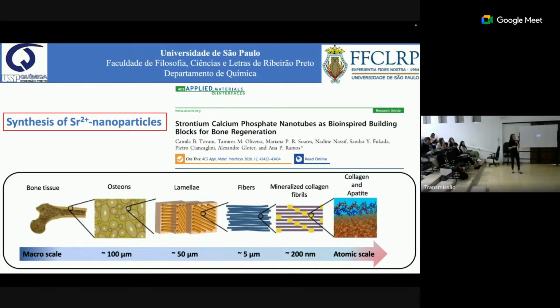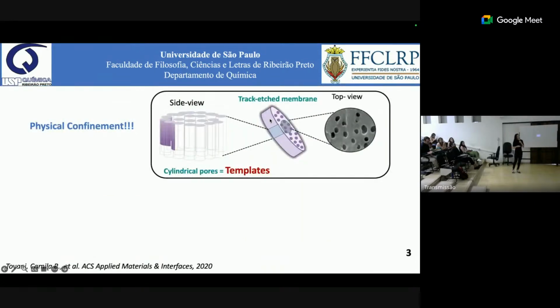I can try also to imitate the structure of mineralized collagen fibers using the synthesis in confined medium of calcium phosphate nanotubes. So here we used track-etched polycarbonate membrane, and we precipitate minerals inside the pores of these membranes. The pores of the membrane had the same diameter as the mineralized collagen fibers.